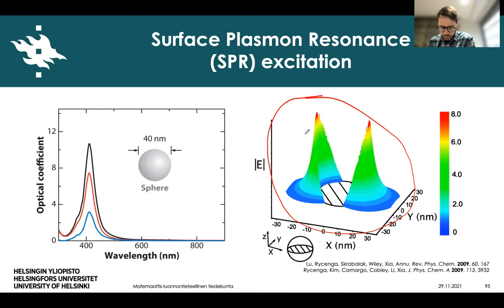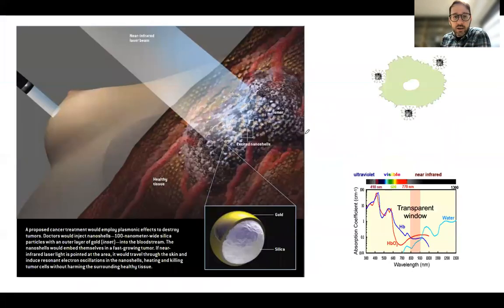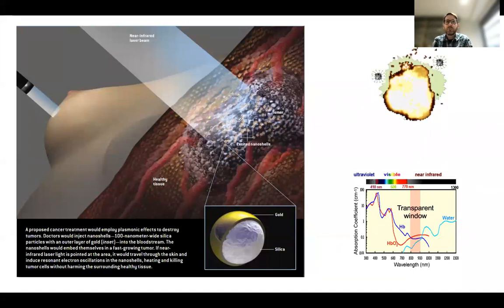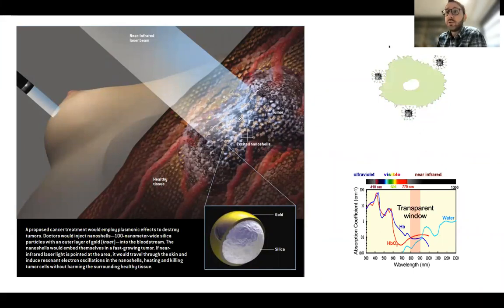So these absorption and scattering properties have been employed, for example, in imaging, and these intense electric fields to enhance the spectroscopic signal of several molecules, enabling under certain conditions detection at the single molecule level. And the localized heating as a result of these interesting optical properties has been employed, for example, to photothermal therapies to treat cancer, in which we can add these nanoparticles selectively to regions containing the tumor. Then we can shine a light in this system, and the light will excite these electrons, and this excitation will dissipate heat to the surroundings, and this heat will therefore kill the cancer cells close to the nanoparticles.